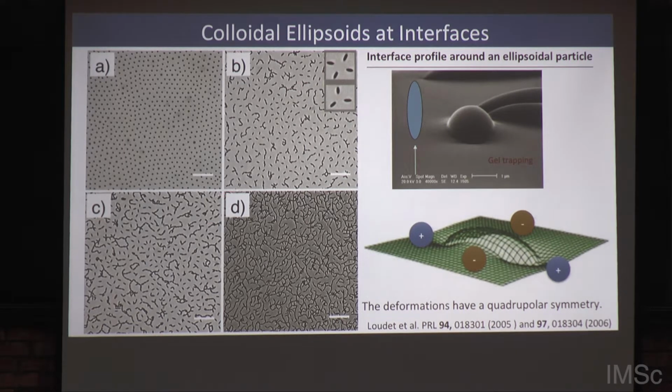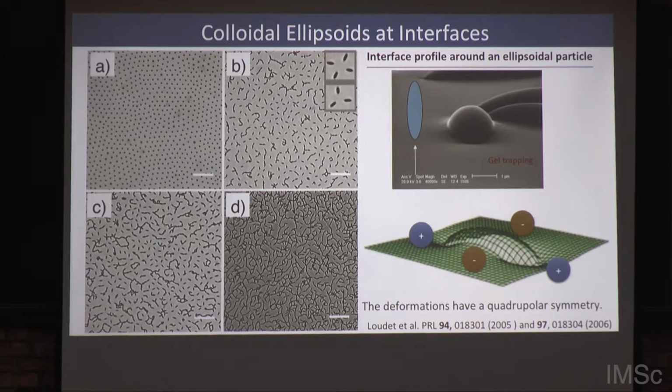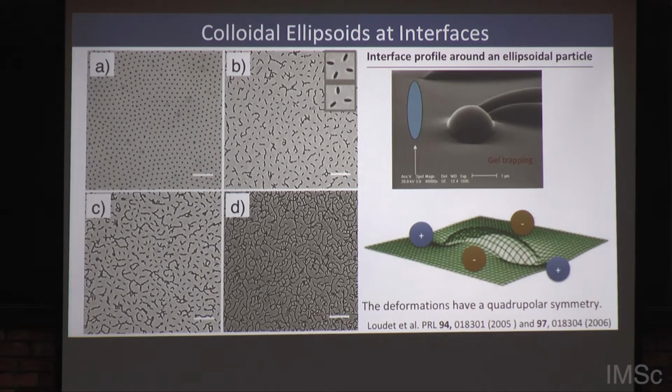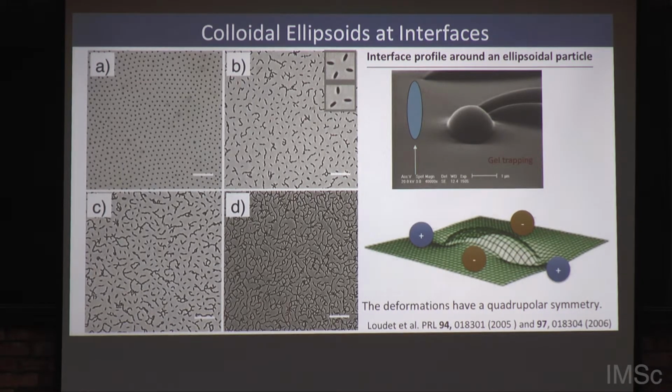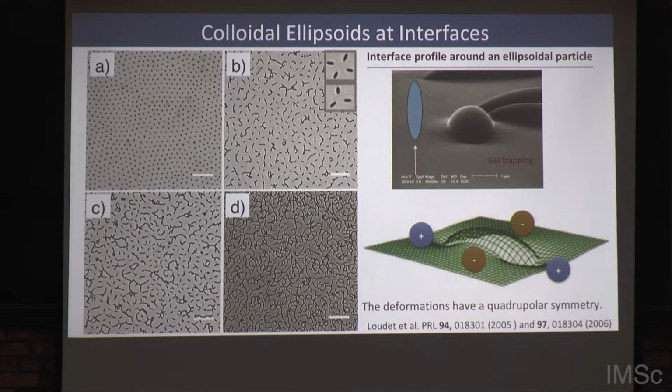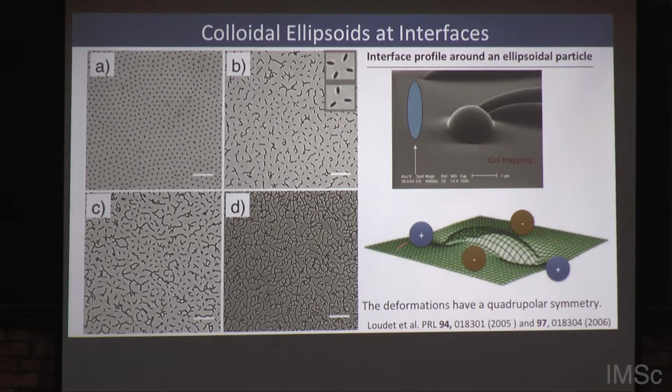In this case, because the particles are charged, we are mostly seeing tip, but we have also done experiments where the particles are a little more weakly charged than what we have used here. In such cases, we mostly see the side arrangement. So the assembly is governed by these shape-induced interface deformations that lead to these nice and interesting structures.